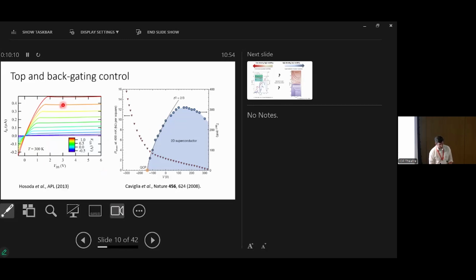So we showed actually from the top side, you can get virtually ideal transistor properties. This was actually at room temperature. So that was very easy to do. Looks textbook-like, fantastic. And again, the group in Geneva showed from the back side that you could remove electrons from the system. And now this is blue data to focus on. This is the superconducting transition temperature as a function of gate voltage. And you could basically pull out all of the electrons and switch off the superconductivity.